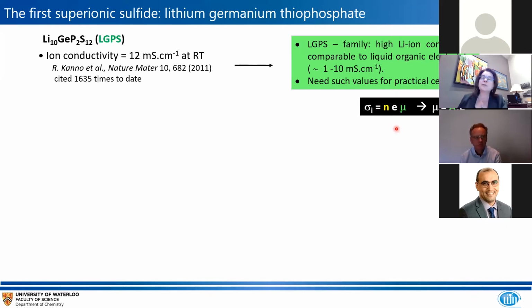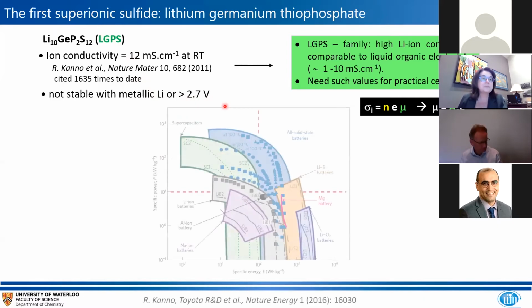And I'm just going to remind you, or perhaps let you know, that conductivity is a function both of the mobility and the number of carriers. And the mobility is a function of what's called a pre-exponential factor, and especially important is the activation energy for the process. So when we try to develop new solid-state ion conductors, we worry about minimizing the activation energy for transport and maximizing the number of carriers. Now, the problem with LGPS is that it's not stable with metallic lithium because the germanium reduces, and it's also not stable at high potential.